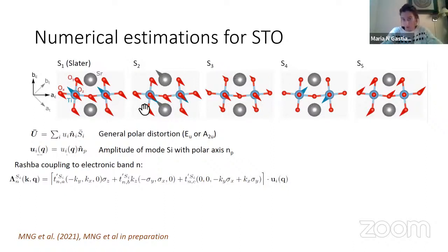This mode will also have a finite contribution from this phase. So what we did was find a way of mapping the entire phase space in terms of the coupling, and then once you get different possibilities for the particular eigenvector for the mode, you can get an estimation. But now, for simplicity, what I'm going to assume is that this mode is completely well described by this S1, this Slater mode. But I just wanted to mention that in principle you can get the full picture and make the mode a little bit more complicated.